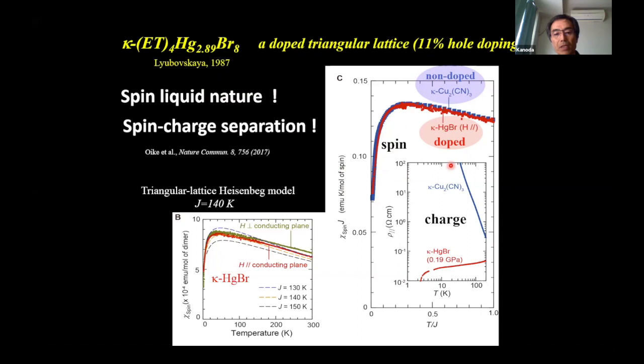Please take a look at these figures. Spin susceptibilities normalized to J for two materials. This is a spin liquid non-doped material, blue symbols. And red symbols indicate the spin susceptibility of this 11% hole doped system. The two materials show nearly the same spin susceptibilities. However, the doped material shows a good metal. So the charge degrees of freedom show a dramatic change. However, the spin sector does not change. So these hole-doped materials can be regarded as doped spin liquid materials.